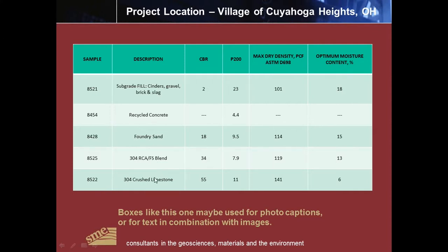When you compare this to the crushed limestone, it had a CBR of 55, P200 of 11%, a slightly dirtier material. Maximum dry density was quite a bit higher at 141, and an optimum moisture content of 6%.